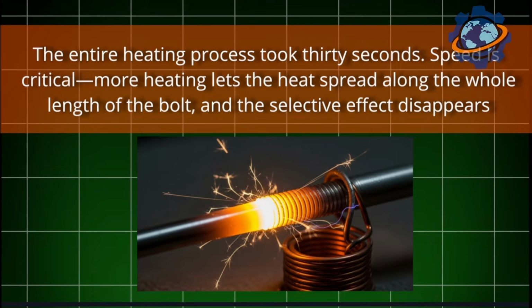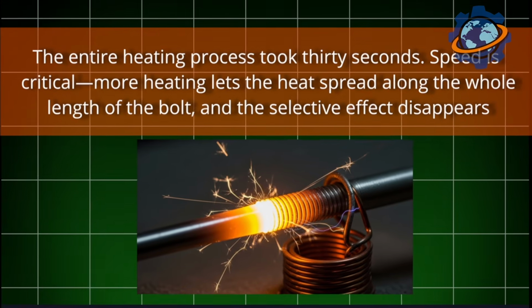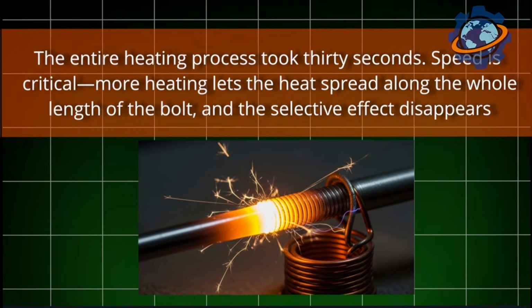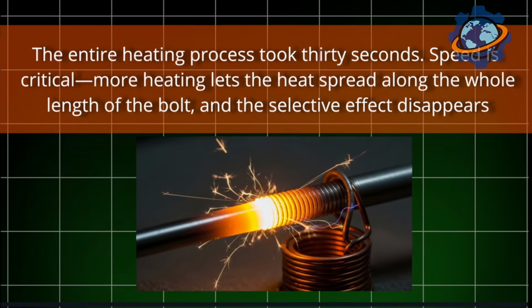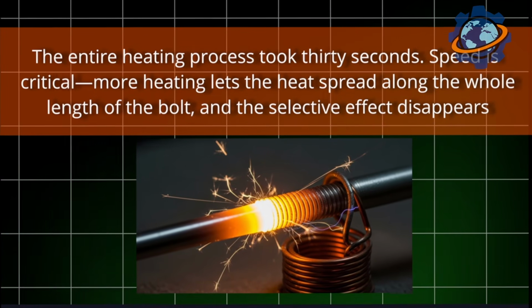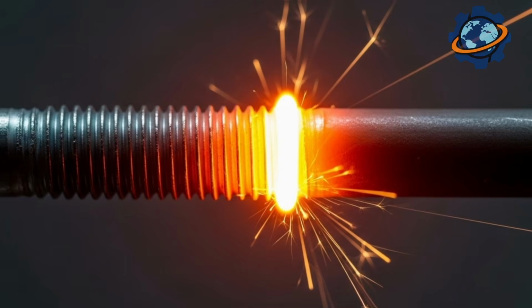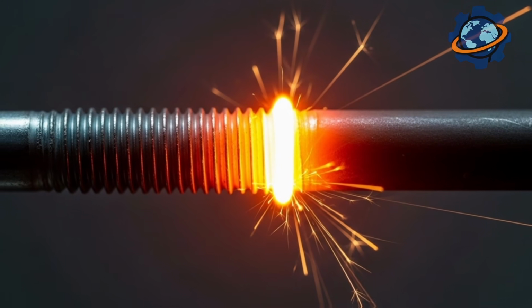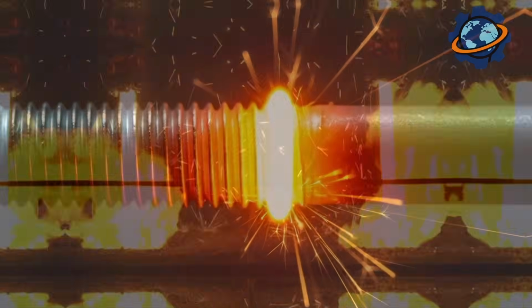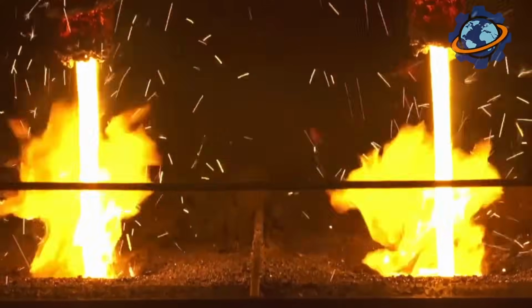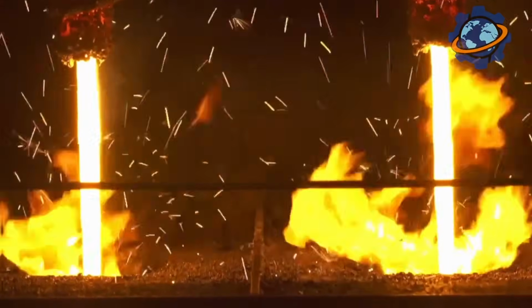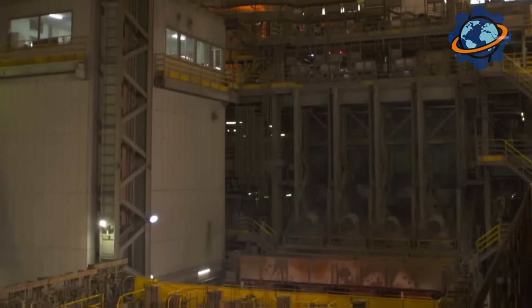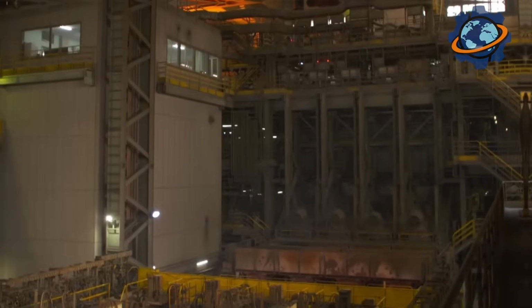The entire heating process took 30 seconds. Speed is critical. More heating lets the heat spread along the whole length of the bolt, and the selective effect disappears. The moment the right temperature hit just the needed spot, the bolt was instantly plunged into a bath of polymer quenching solution. The sharp temperature drop transformed the metal structure in the head into super hard martensite.